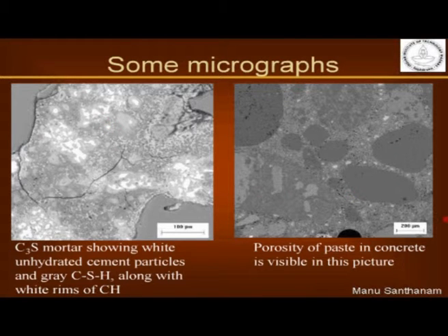If you look at the concrete image under the microscope, you see several large aggregates, smaller aggregates, and the zones in between occupied by cement paste. Now the thing is, if you look at the overall picture of concrete, about 80% of your image seems to be only aggregate, only 20% of the volume is looking like cement paste, and that is exactly what you have in normal concrete, that only 20% of your normal concrete is actually cement paste, remaining is just aggregate.